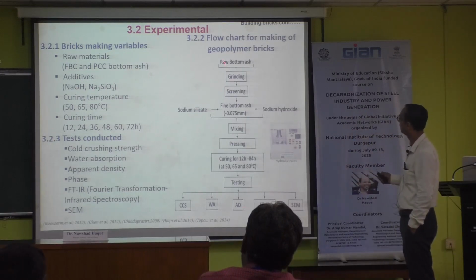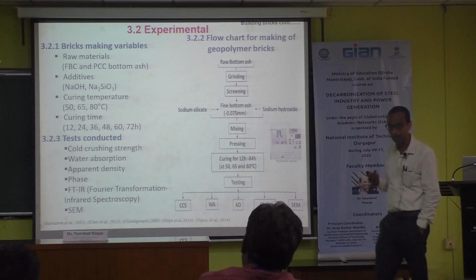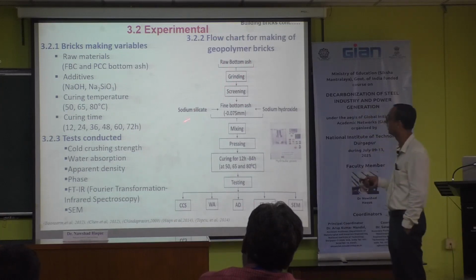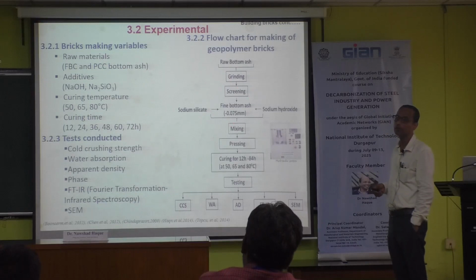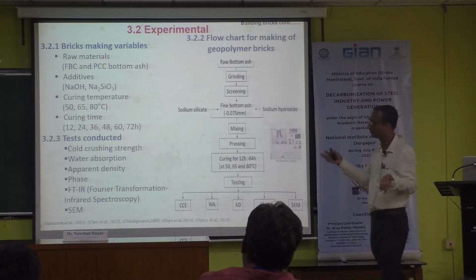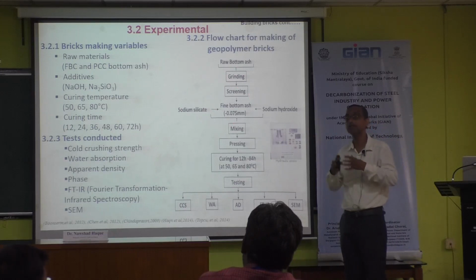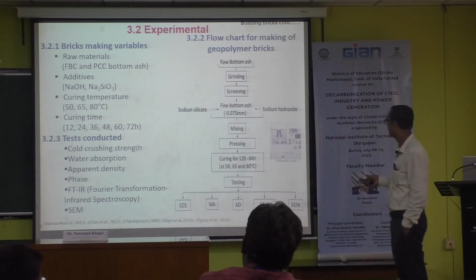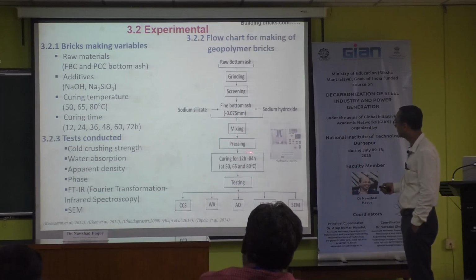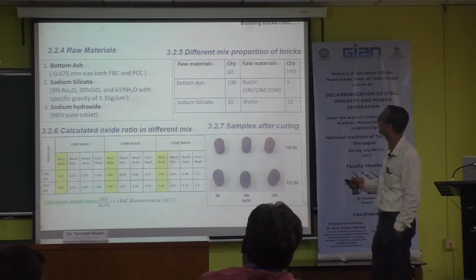Then this is the project on bottom ash. Grinding is required because bottom ash has a higher particle size and coarse nature, so they have to grind. Why is grinding required? To get more surface area, because the geopolymerization reaction requires higher surface area. Then we mix it with pure and distilled water, with different properties. The bottom ash is 0.075 mm size, both FBC and PCC, and sodium silicate in this concentration and sodium hydroxide are added.